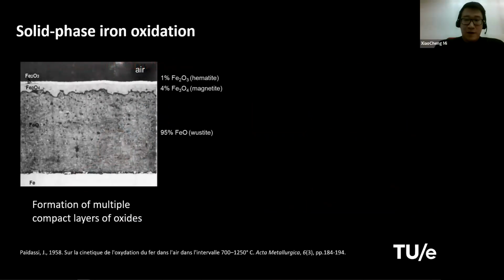So iron particles are stored in solid phase. So to start combustion, first of all, the reaction must happen in solid phase, right? And to understand the solid phase oxidation mechanism really allows us to understand the ignition process of iron particle. So this, we can find some information from this 1950s metallurgy study. They studied how this iron oxide scales build up on a sample of iron.